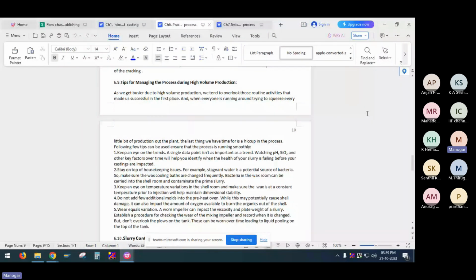Some of the tips during the process for high volume production: keep an eye on the trends, not the single data. For the process control points, pH, SiO2, make a chart, study it and regularly monitor what changes are going on. Depending upon the season, then you have to alter. On top of that, housekeeping issues, for example, stagnant water is a potential source for bacteria. So make sure that wax cooling baths are changed frequently. Bacteria in the wax room can be carried into the shell room and contaminate the slurry.